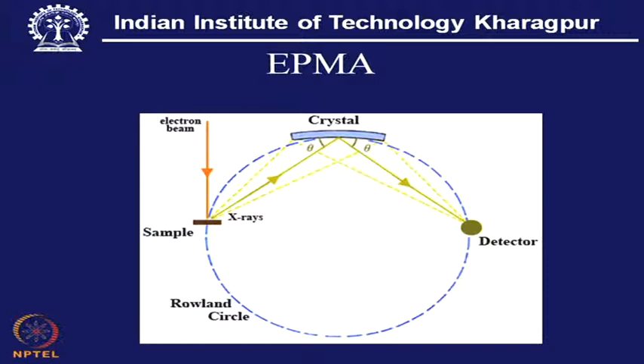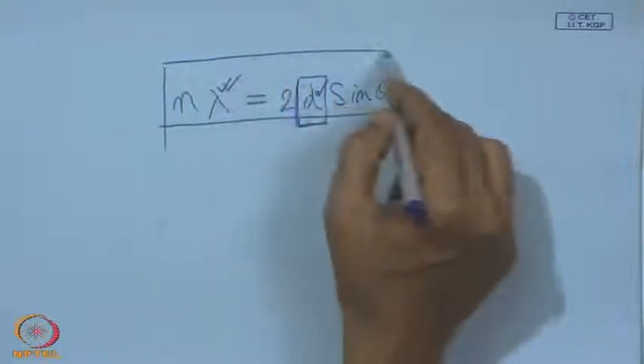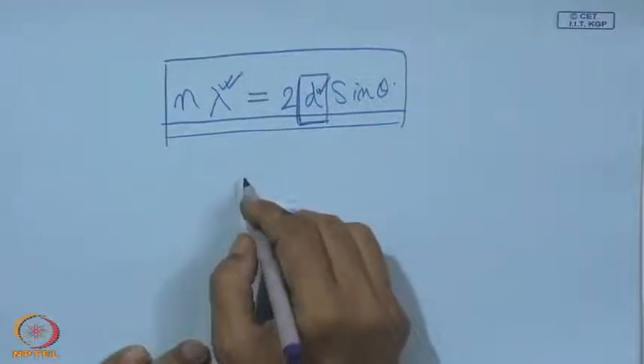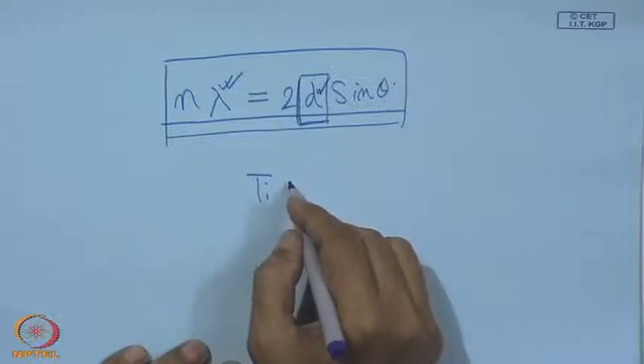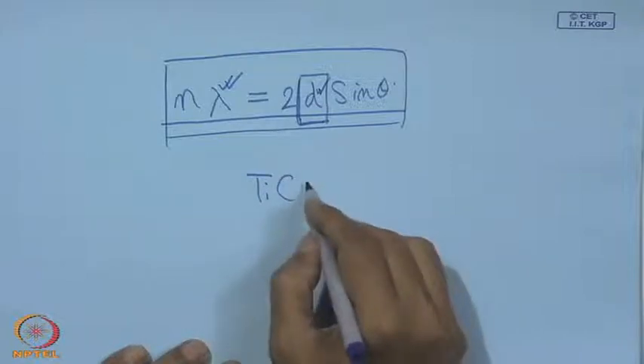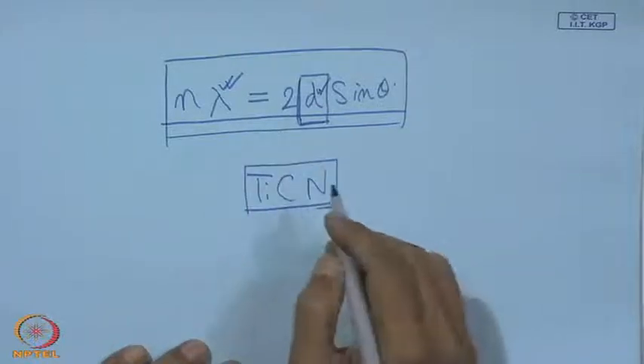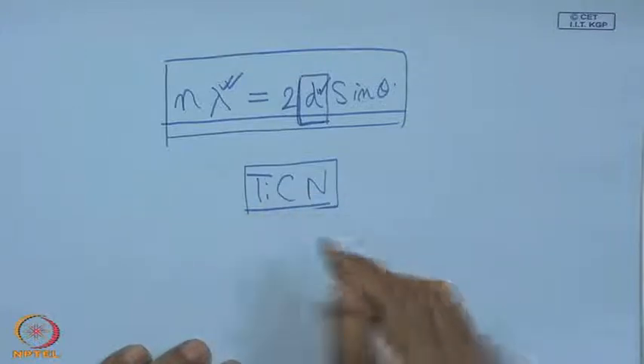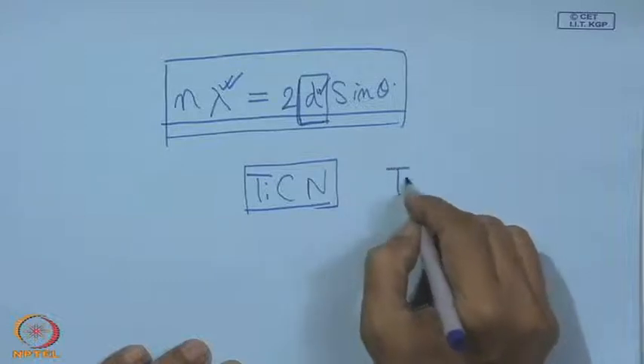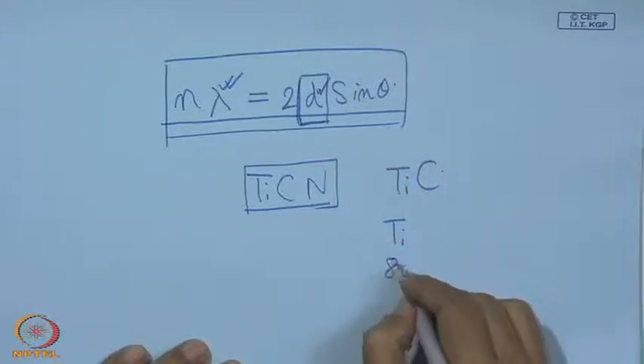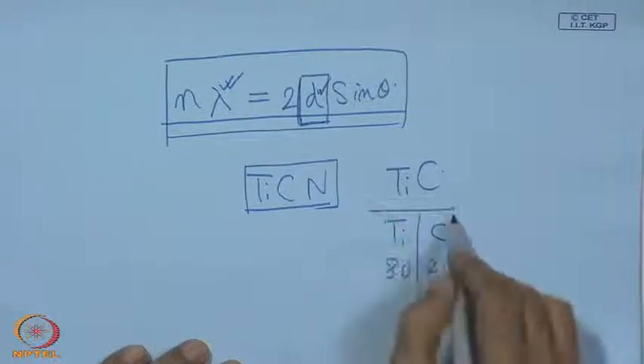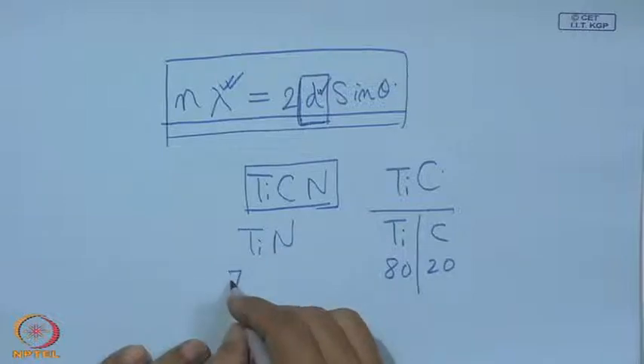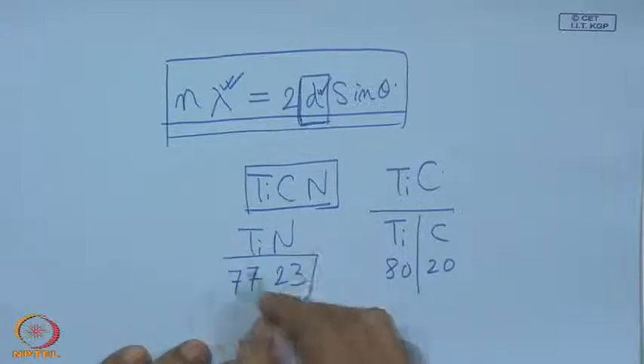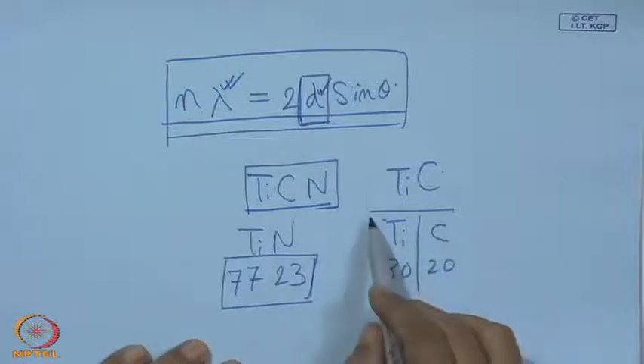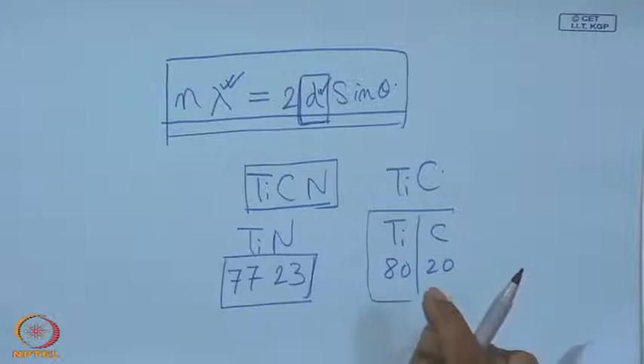And this beam and detector can also probe over the surface. So, with this we can find not only the composition but the quantification of the composition. Say it is TiCN, so the value of titanium, carbon and nitrogen. For example, for titanium carbide it should be, say, 80% titanium and 20% carbon by weight, or if it is titanium nitride, for example, it will be 77% and 23%.